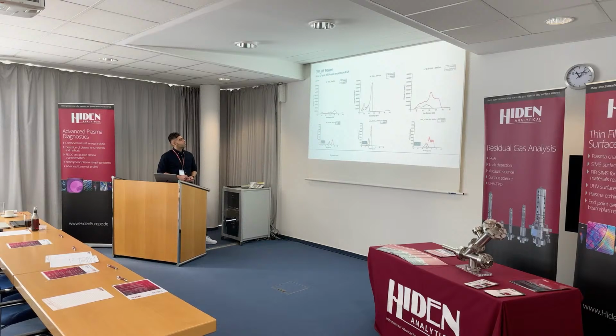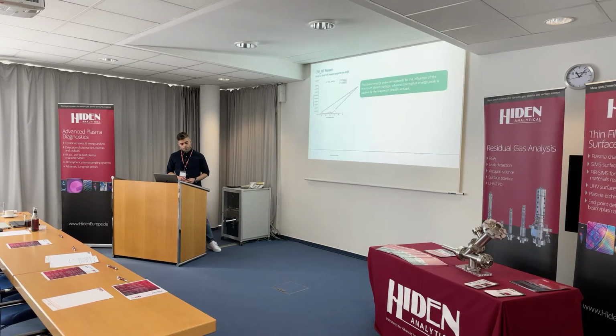This is the HF only. So the LF power is off and we only increase the power for HF frequency, and you see the increase in integral intensity and also an increase in ion energies. And this is the effect of both LF power and HF power. So you see an increase in this direction. That's why we see two peaks in our IDFs.